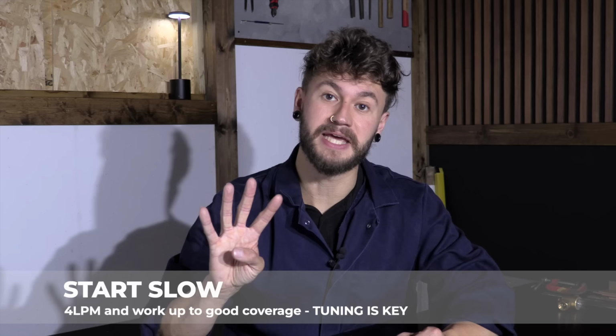Let me explain. Your shielding gas, in our case argon, exits the TIG torch at whatever rate we set it to. It's heavier than air, so it falls and settles over the weld pool, and it hangs around long enough to protect it whilst it cools. Now, unless you're using a massive cup and have some back purge or trail set up, because the gas has to exit the small orifice of the torch, turning the flow rate up adds pressure to the stream, causing it to jet out at speed.